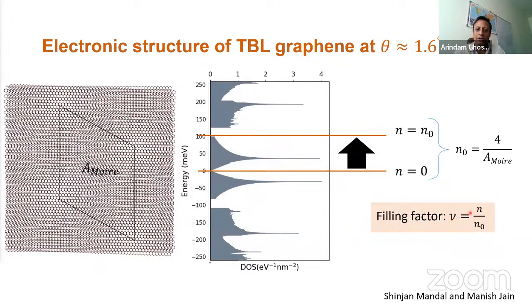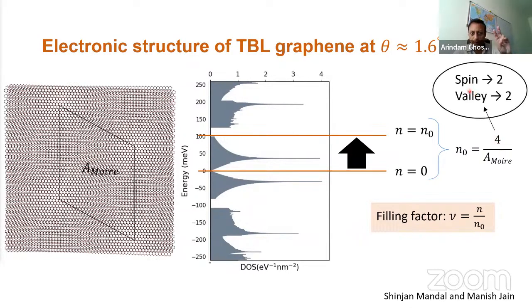The filling factor is new. If this band can contain at the most N0 electrons, or Ns, which I'm going to use later, then the density that exists divided by the maximum density that you can put in this band is called a filling factor. And N0 is nothing but the 4 comes from spin, 2 spins and 2 valleys, and that gives you 4, divided by the area of the Moire cell, and that gives you the maximum number of electrons or holes you can put in any of these bands. So the filling factor is essentially the density divided by the maximum that you can put in over there.